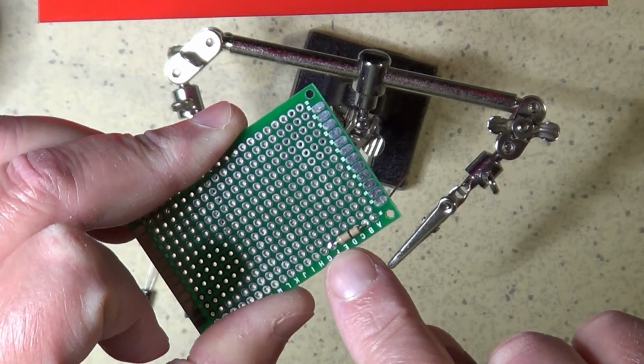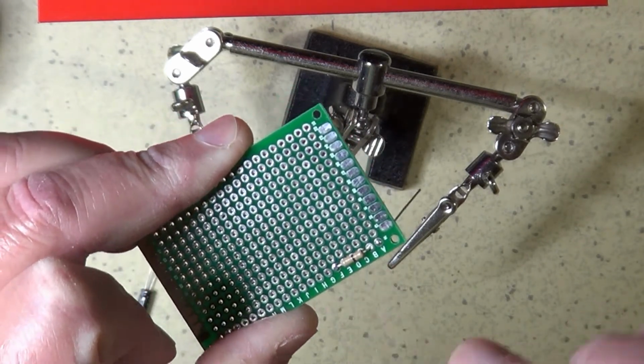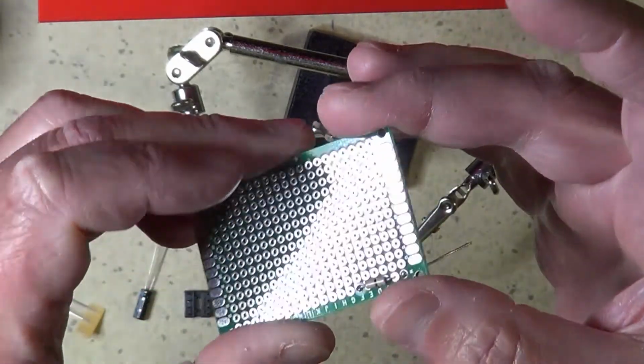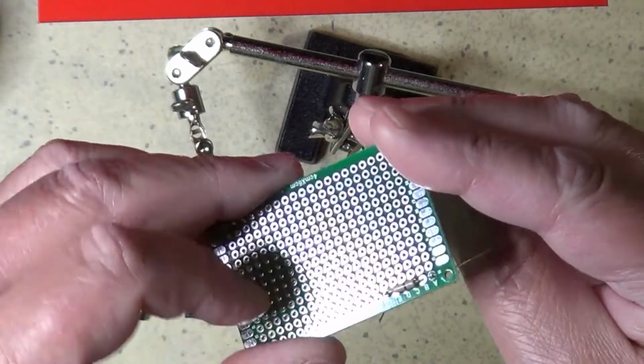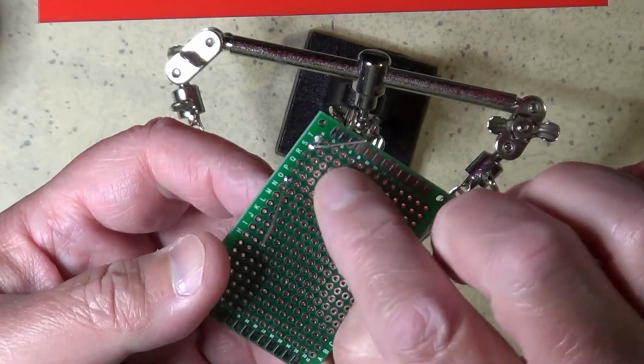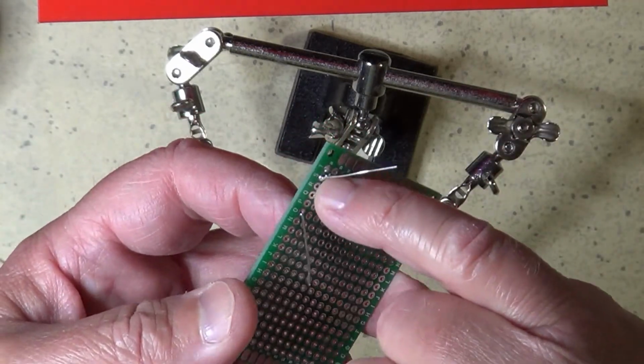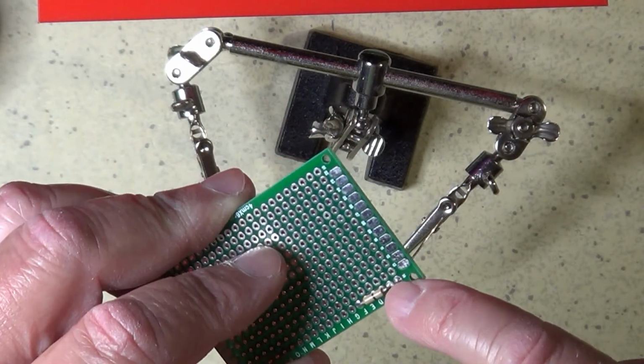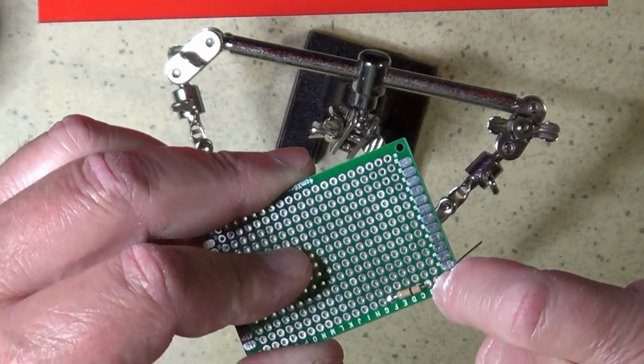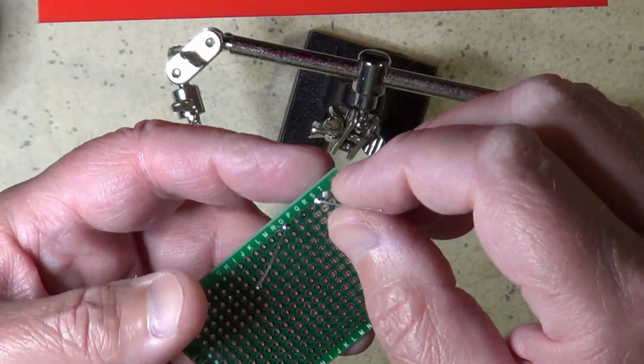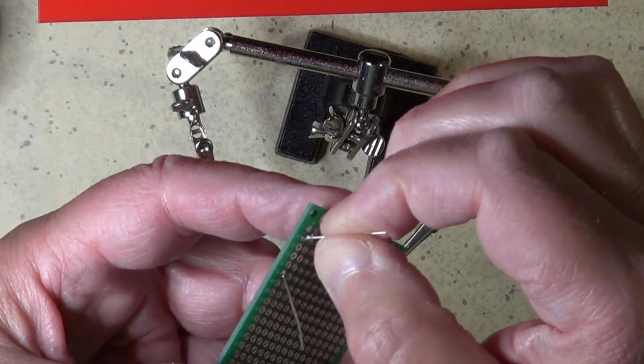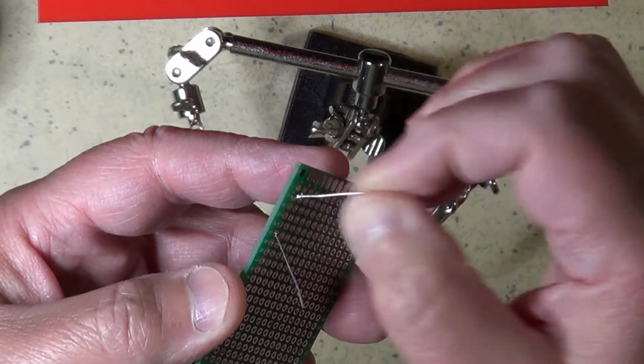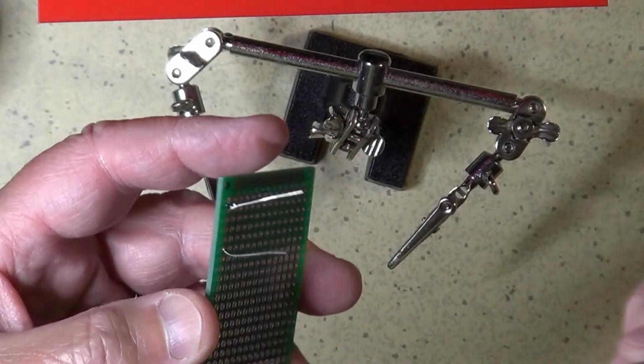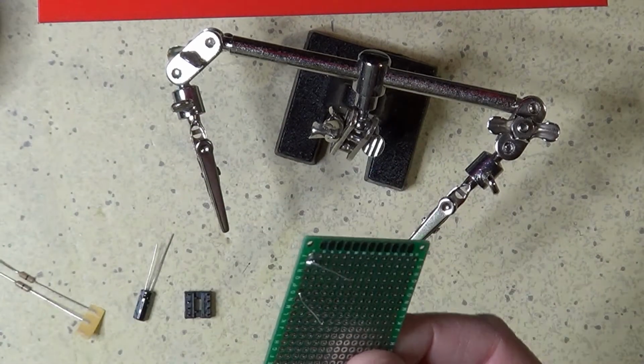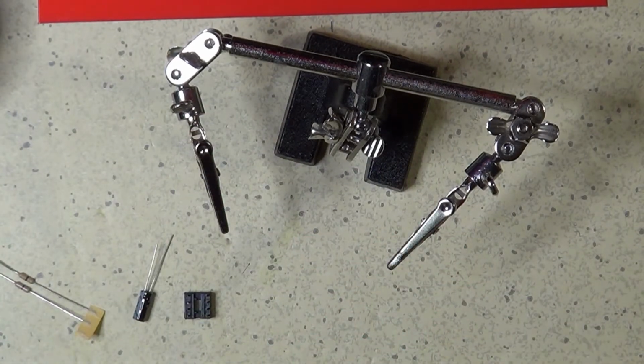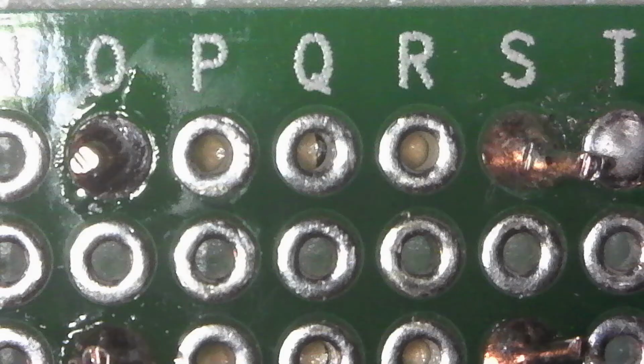It is what is called a cold soldering, because the pad and the wire were cold when I put the solder on top of them. The solder cooled immediately and crystallized, making the surface look matte. If we look at the other side of the board, at least in those cases where we have a double-sided board, you can see how, with the right procedure, the solder spread also on the other side. With the wrong procedure, instead, the solder does not spread to the other side, or it spreads unevenly.